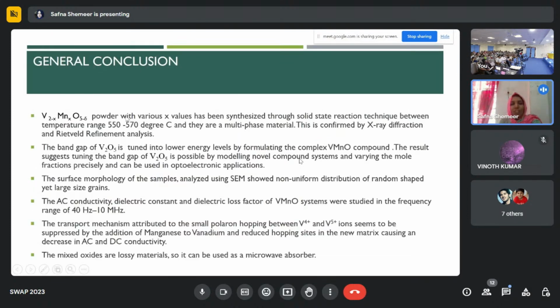Let me conclude my observation. We synthesized V2-xMnxO5-δ samples through solid state reaction technique, and they are a multi-phase material. And this is confirmed by XRD and Rietveld refinement analysis. And also the band gap of vanadium pentoxide is tuned into lower energy levels by formulating the complex VMNO compound. The results suggest tuning the band gap of vanadium pentoxide is possible by modeling novel compound systems and varying the mole fraction precisely, and can be used in optoelectronic applications.